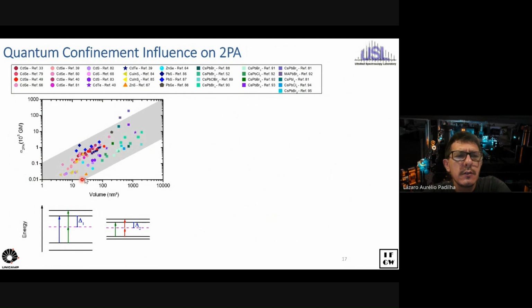And this is all this data as a function of the quantum dot volume. And that's for cadmium selenide, cadmium sulfide, cadmium telluride, CIS, zinc sulfide, zinc selenide, lead sulfide, lead selenide, and a bunch of perovskites. And we see that they are all spread around here.